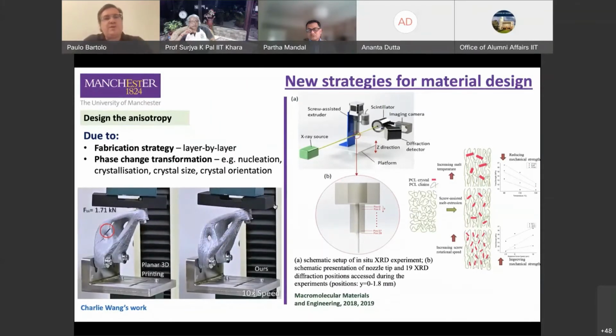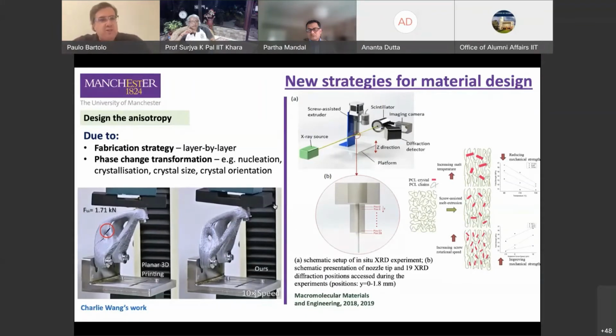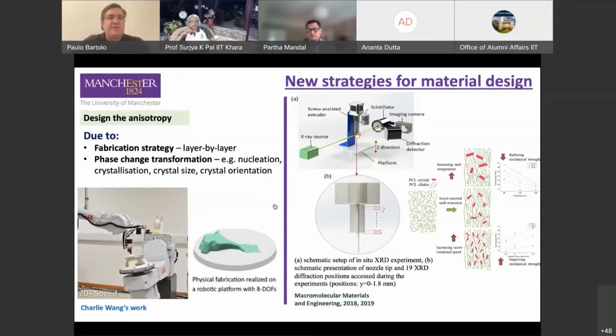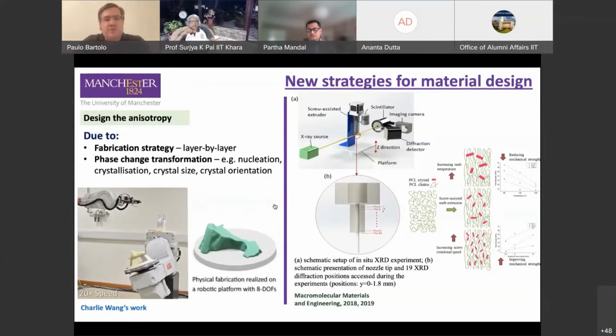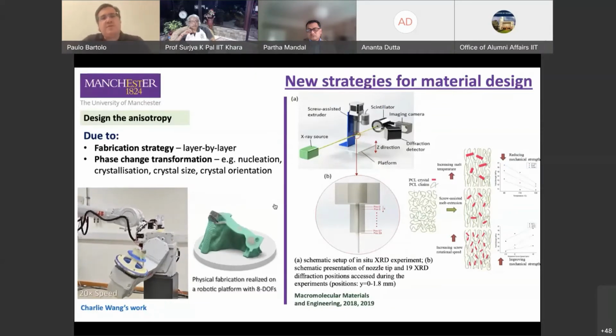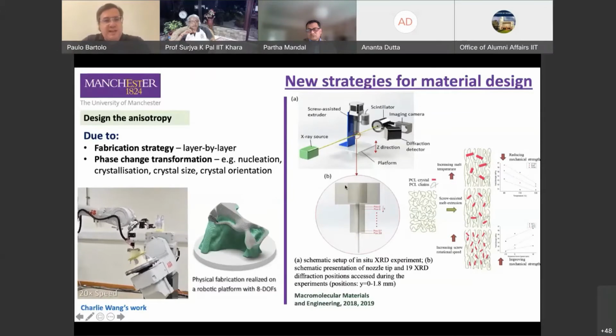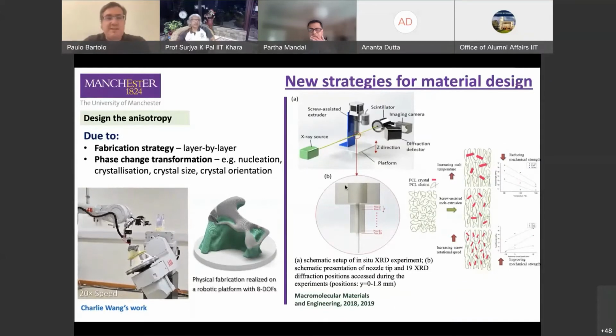And basically what we are trying to do is to correlate processing conditions with the morphological development, the effect of these processing conditions on the crystallization process, crystal size and crystal orientation, and the effect of it on mechanical properties. Two years ago, again, we published some papers. So we published also some papers before. And my group was the first group to investigate the in situ morphological development during the printing process using synchrotron. And we started creating models correlating all of these. And we are now designing a new printing head, another totally new printing head, allowing us to control the processing conditions in real time, allowing us to design the anisotropy of the final structures.